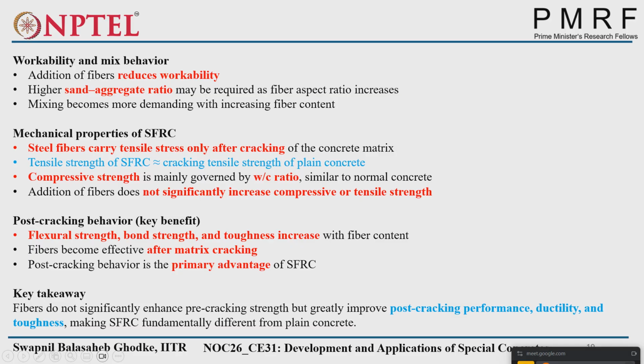Fiber becomes effective after matrix cracking. Then only fiber will come into picture. Suppose we have a concrete beam, and once the first crack appears in the beam, then only the fibers' effectiveness comes into picture. So post peak behavior or post cracking behavior is the primary advantage of steel fiber reinforced concrete.